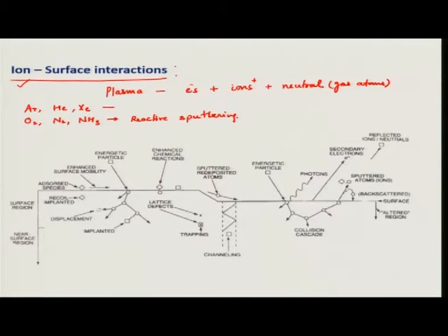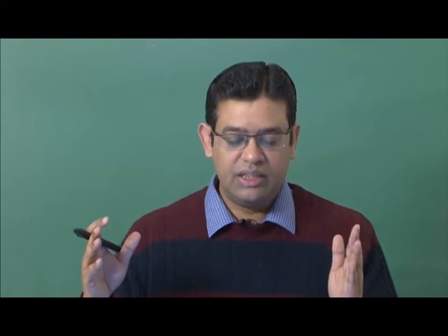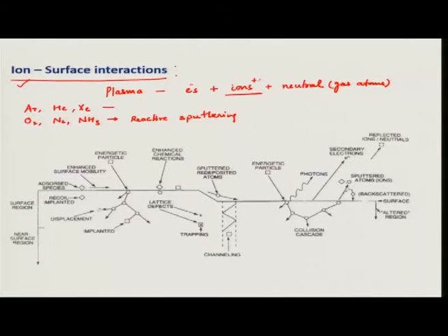Now, for sputtering process we are mainly interested in these positively charged ions. If you recall our cathode, which is a negative electrode, all positively charged ions will be accelerated towards the cathode, in the electric field which is applied between the two electrodes. Now, these positively charged ions which have some kinetic energy, when they collide with the surface of the cathode, there are many activities that happen on the surface.